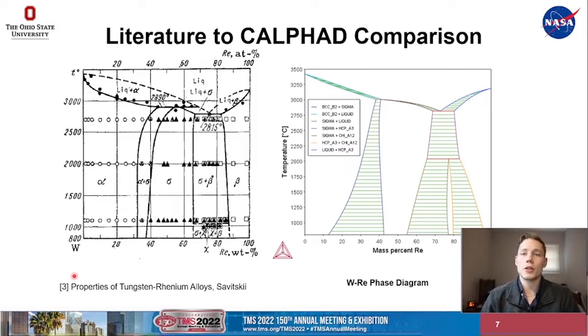To start off with, we wanted to compare CALPHAD calculation of phase diagrams results versus literature results. So on the right here, we have a tungsten rhenium binary phase diagram that was produced through the use of CALPHAD software. And then on the left, we have the literature version of the tungsten rhenium binary phase diagram. As you can see, there was good similarity between these two diagrams, providing confidence that the thermodynamic software is modeling the system well, and the database that we're using as well is very important.